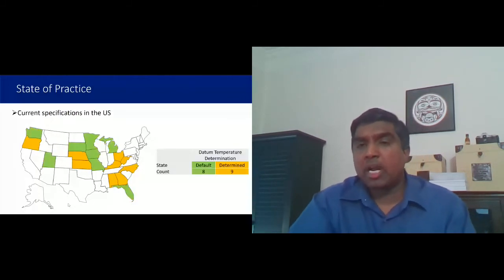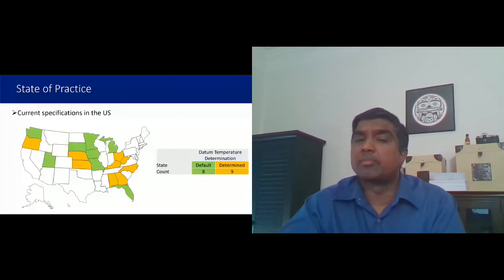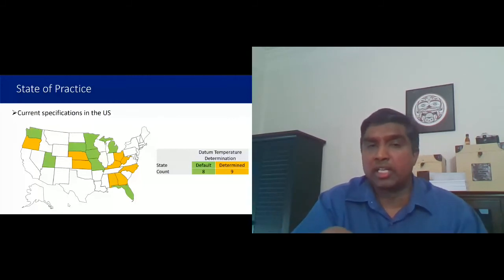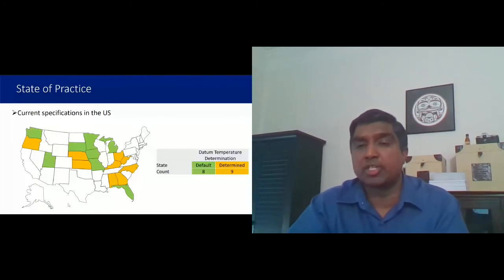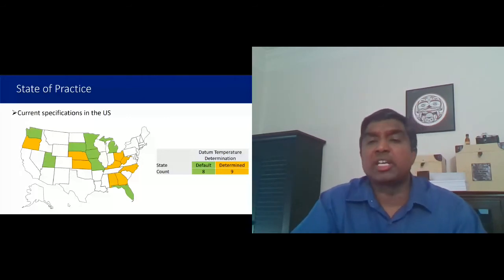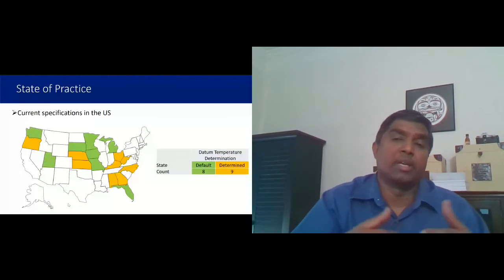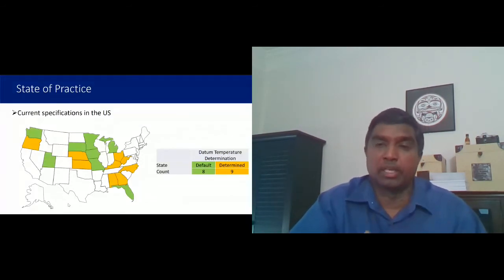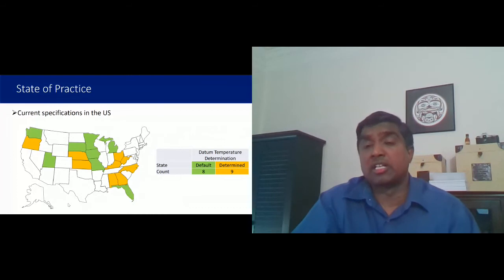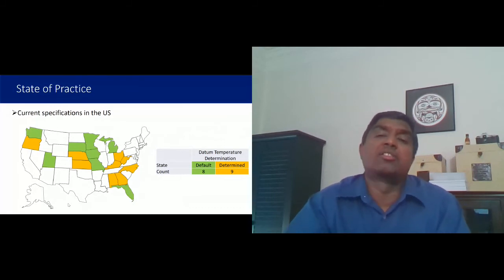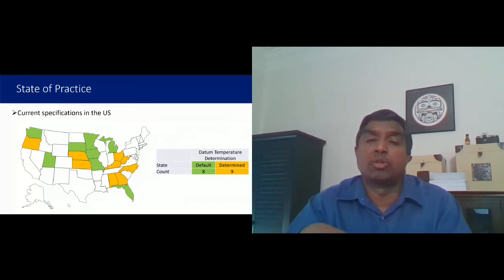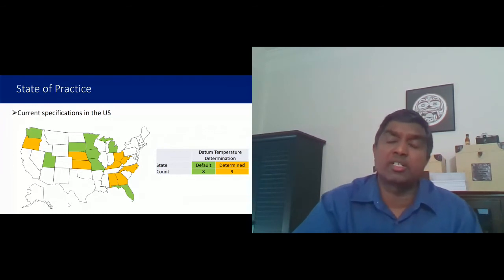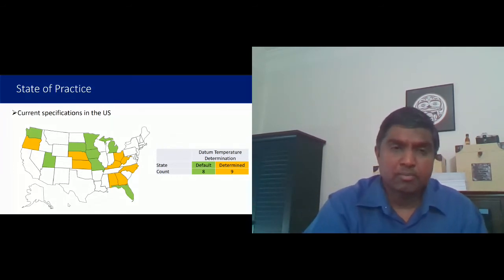Now, if you remember, I was also talking about the datum temperature determination. In the states that do specify maturity, half of them basically recommend that the contractor use a default number, either -10 or 0 degrees Celsius. And in some states, they do require the contractor to determine the datum temperature. Again, all of that information is in the ASTM test method.